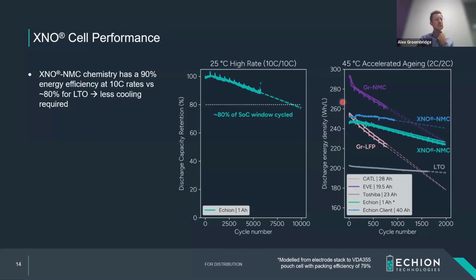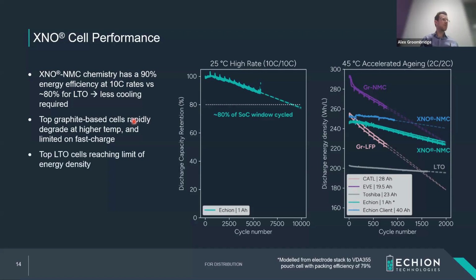Other effects worth mentioning is energy efficiency. It's a bit more nuanced, but the energy efficiency of our XNO chemistry is higher than that for an LTO chemistry, 90% versus 80%. What this means is we generate less heat by operating at higher C rates. So when you think about modules and packs and mining vehicles, you don't want to have to mitigate that heat if you can avoid it, because all batteries degrade faster at higher temperatures. And I've spoken through these other bits. So the XNO is providing that higher C rate, temperature stability, and long life that we need.